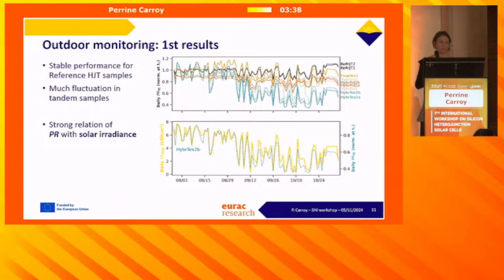more. And in particular, we see a strong relation with the performance ratio. So with these cells that perform much worse on the cloudy days and then recover on the sunny days. And for some cells, it's really like a perfect correlation.